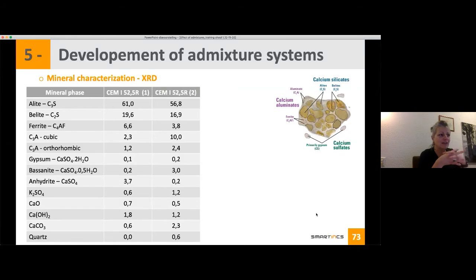What we need to consider is that when you have a CEM I 52.5 R, it doesn't mean that all cements have exactly the same composition. If you have supplier 1 and supplier 2, both cements will comply with the cement norm, and they will have the strength and the requirements in a norm mortar. But if you look at the phase distribution, you see a significant change inside the composition.